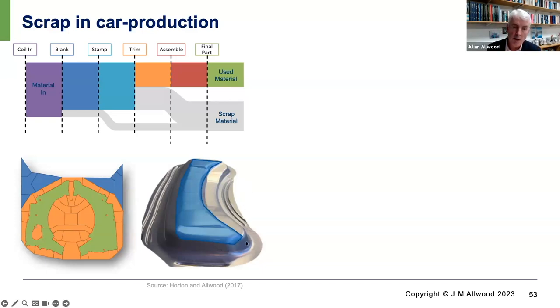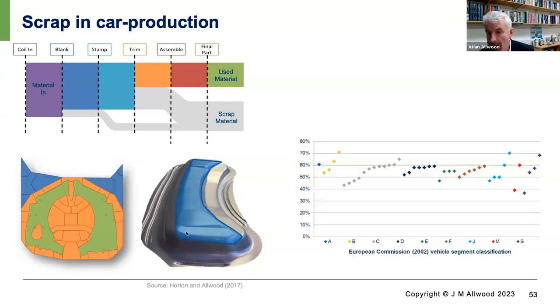We have to grip the material around the edge as we squash it between a male and female die. And in doing that, we prevent wrinkling, but we then have to trim off all the excess material beyond what we actually need in the car. And when we look at real world data, which is published by the car industry on some frequency, we found that the average utilization was about 50 to 55% across all classes of car. Luxury cars naturally are slightly worse. So the car industry, roughly speaking, is generating as much scrap as it's generating cars because of deep drawing.